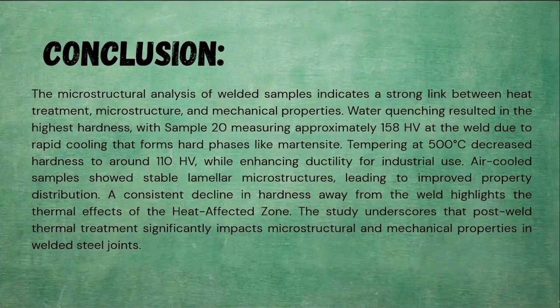For the conclusion, this study demonstrated that post-weld thermal treatments play a critical role in determining both the microstructure and mechanical properties of welded steel samples. Across all three treatment conditions, which are air cooling, water quenching, and tempering, we observed three consistent findings. First, water quenching produced the most significant microstructural changes. Sample 20 recorded the highest initial hardness at approximately 158 HV at the weld point, owing to the rapid cooling rate that promotes the formation of martensite and acicular ferrite, phases that are hard but brittle.